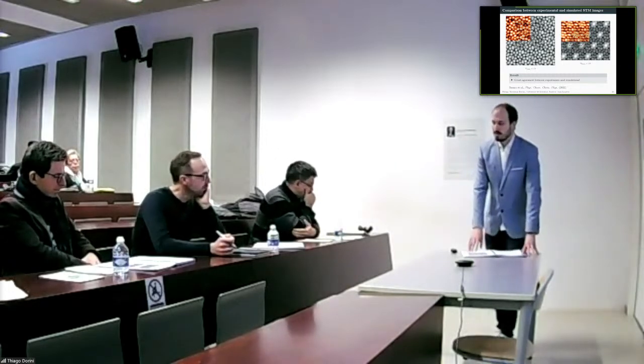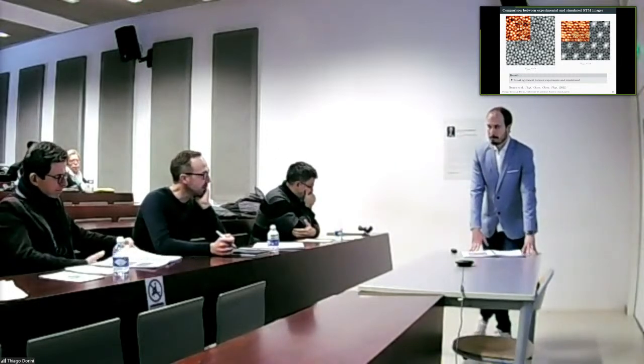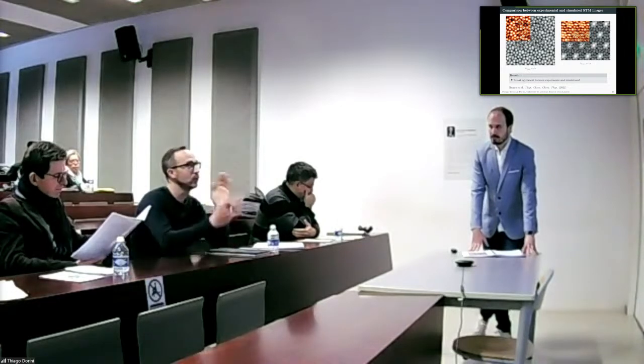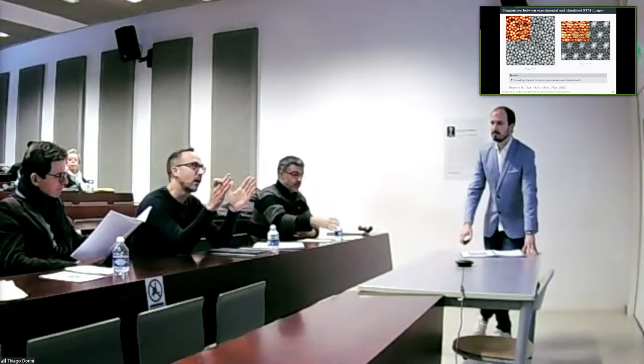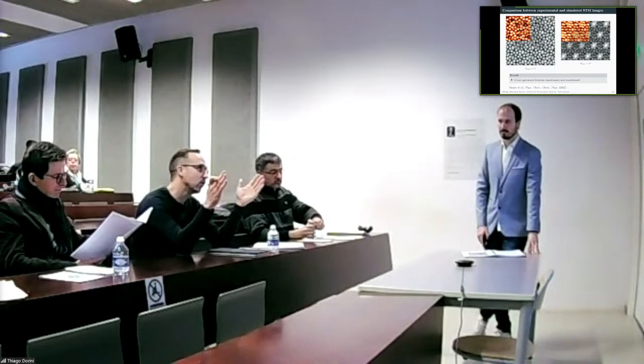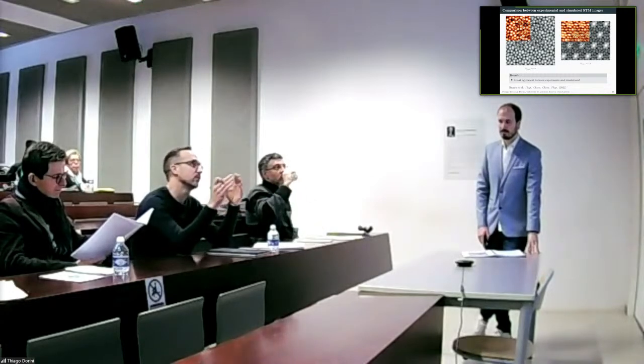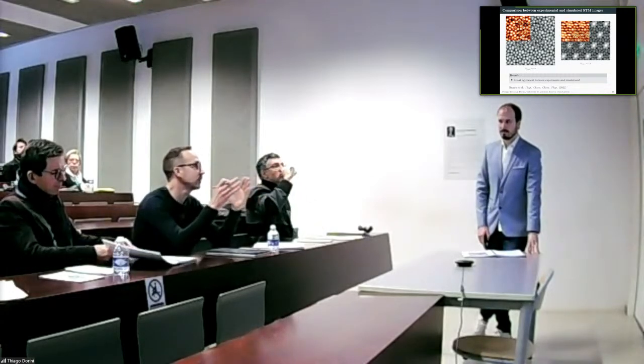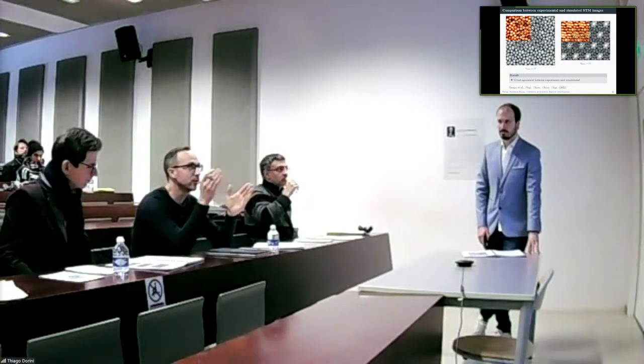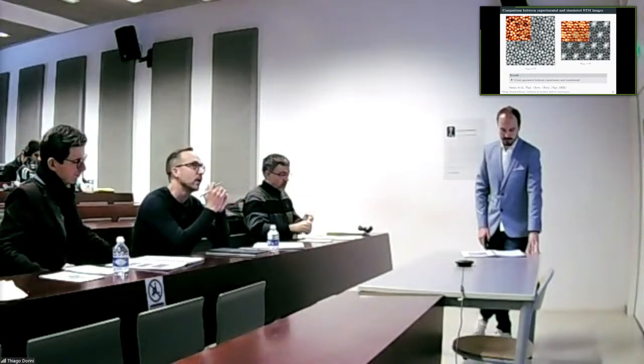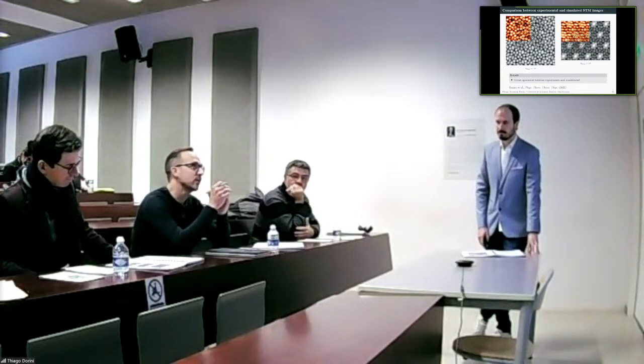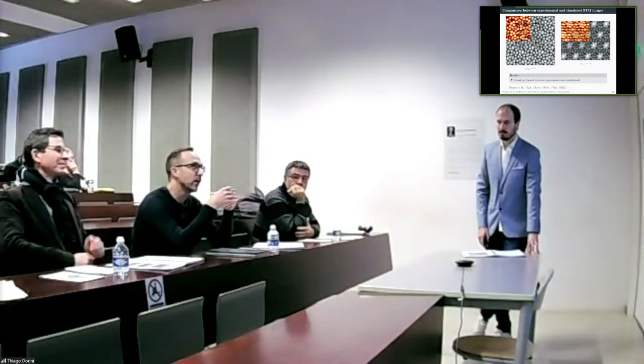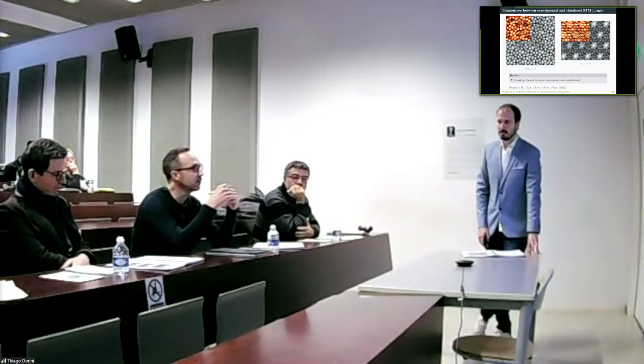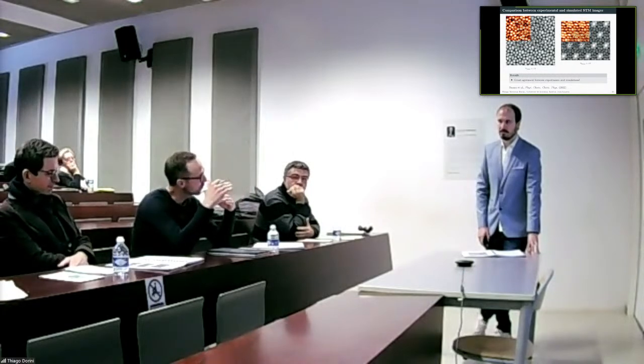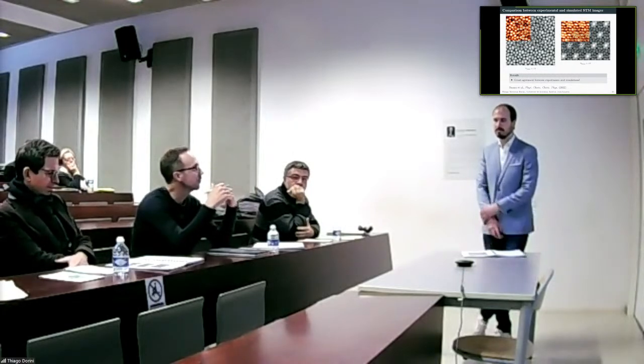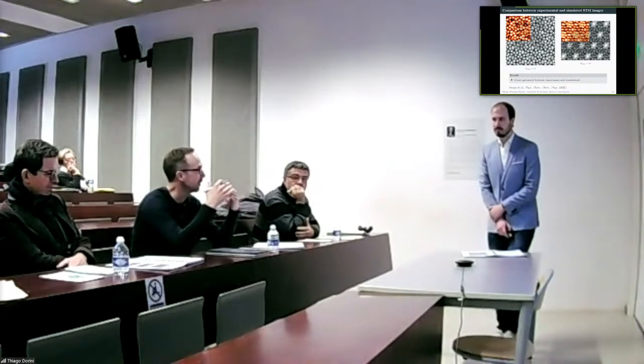And so what I know about scanning tunneling microscopy is that you apply a certain bias, and then you collect all the current which is coming from the integration of the density of states from the Fermi level to the bias that you choose. Yes. And the other thing that I know is that it's exponentially dependent on the distance. So that means if there's some protruding atom which is 1 angstrom higher than the rest, we'll have a current enhanced by a factor of 10.